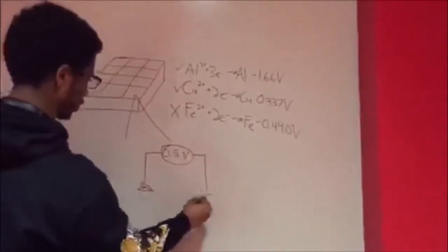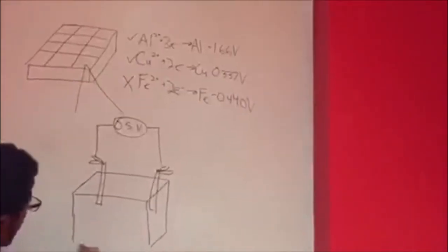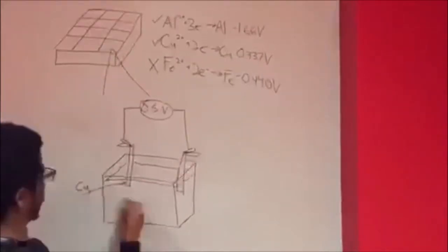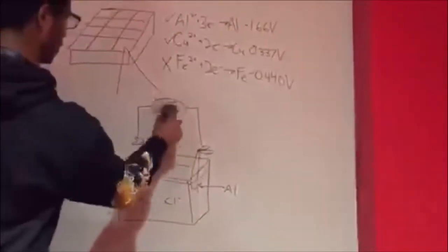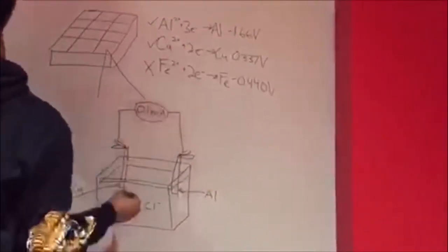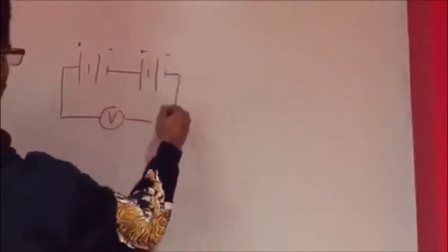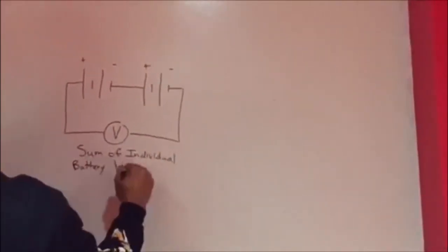Initially, we chose potassium chloride as our electrolyte, and we were able to get pretty decent results. With one cell, we were able to generate 0.5 volts and 0.2 milliamps. By connecting battery cells in series, the cathode of one cell to the anode of another one, you can effectively add their voltages together. So we treated each compartment as its own battery cell and hooked all 12 of them up in series. Doing this, we measured a voltage of 5.7 volts.